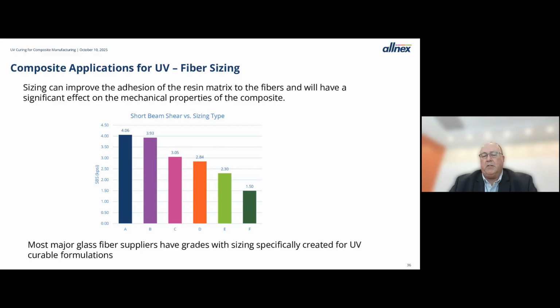So everything was held the same. The glass fibers were the same except for sizing. The formulation was the same. The cure process was the same. And the sizing is the only variable here. And you can see it has quite a big effect on final properties.